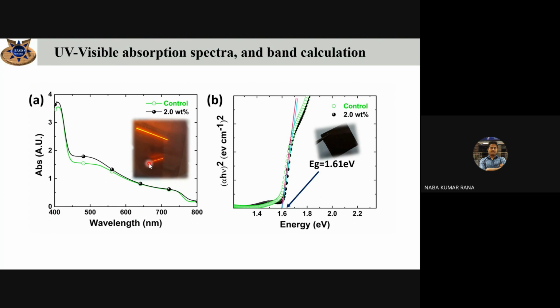film also increases. It means it absorbs more light after the introduction of Al2O3 nanoparticles, but it does not change the band gap of the particular mixed halide perovskite film.